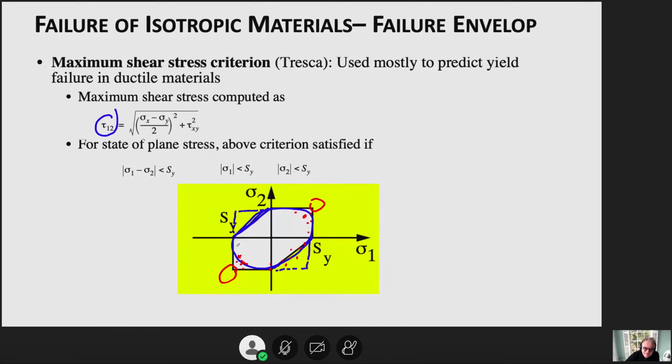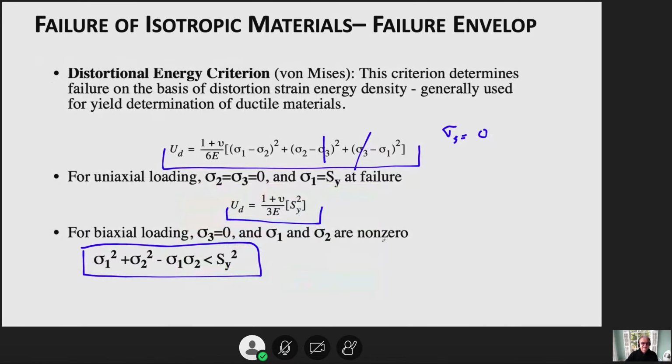You don't reach these points. The experimental data shows that you're mostly going to be around here, with occasional data points in the experiments going outside the boundaries of the ellipse as well. Is it a perfect ellipse from the experiment? It hardly is, meaning that it is probably more complicated, with some chancy events; probabilistic failure events would also influence this failure in materials.